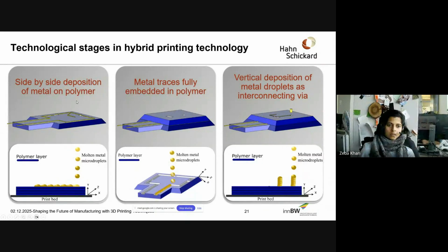In this particular hybrid printing technology, we have some technological stages. The first one consists of side-by-side deposition of metal on polymer. As you see in this image, this side-by-side deposition requires the molten metal droplets to be printed consistently. Even if one droplet goes missing, we will have a discontinuous line. This means that if we try to build up the layer to go to the second stage, where we build the next layer on top, it will not function anymore. In this model, I just showed you a USB plug-in based model that we printed here.